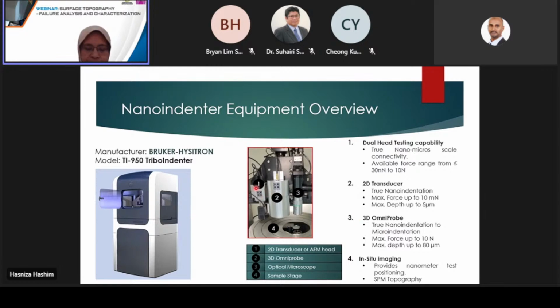For this 2D transducer, the probe can also be used as a contact mode scanning probe microscope, or SPM. There are piezo actuators which can scan the probe at a low force of around 2 micronewtons along the surface, rastering and constantly measuring the displacement of the probe. From that, it can give you a spatial representation and three-dimensional values. So basically you get a topographical map of the area that you want to scan.